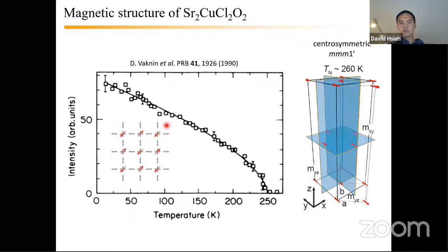This Néel structure is again centrosymmetric. It doesn't break inversion symmetry. And the magnetic point group that it respects is this mmm1' structure. As I'll show you here, all three of these mirror planes, MXY, MYZ, MXZ, are preserved under this antiferromagnetic structure. And 1' just means that it's also invariant under time reversal.